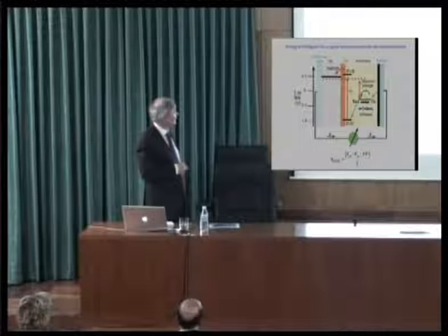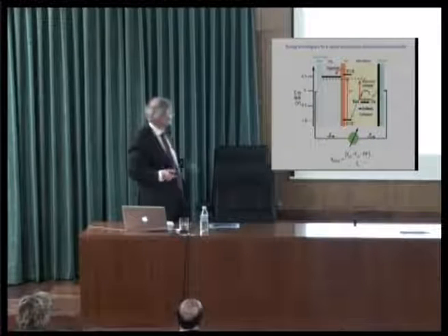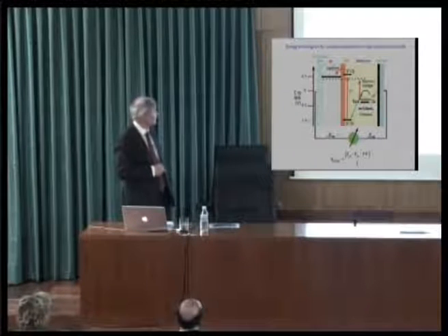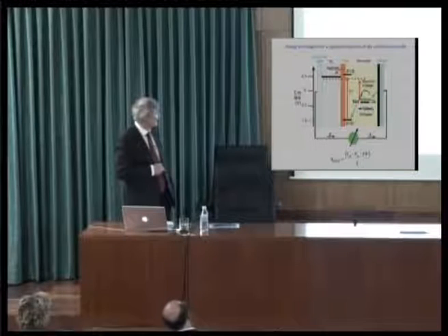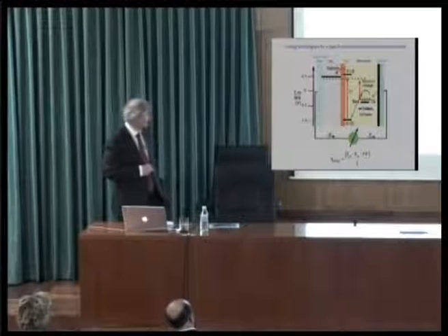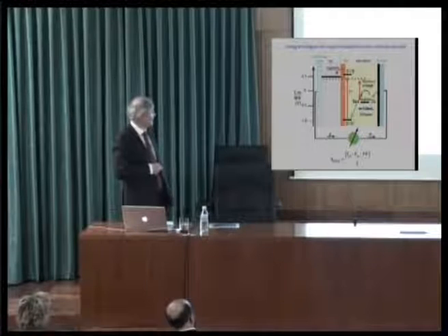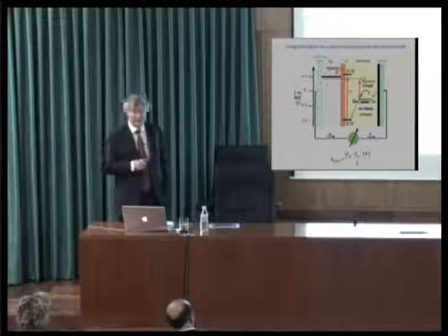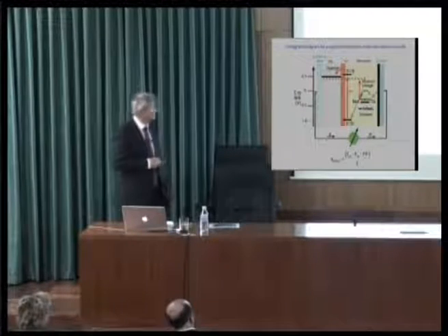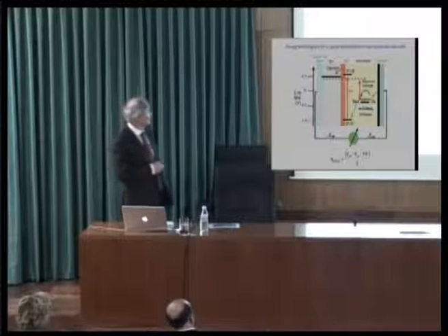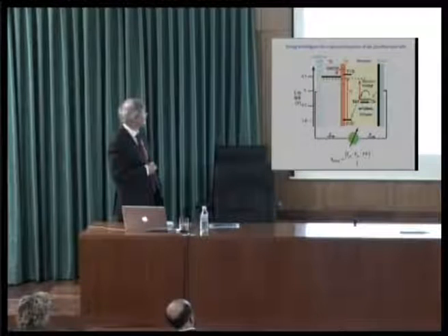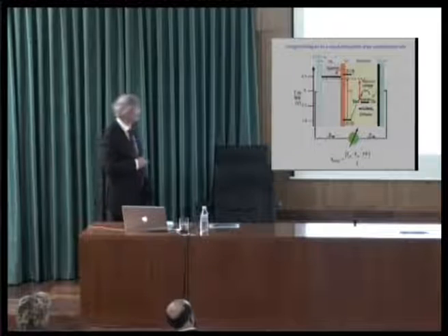Now, the hole is on the dye, the electron is in the oxide. Charges are separated. Now we need to regenerate the dye, using that redox system or hole conductor, but we haven't really matched those levels. So the Fermi level of the solution, or the Nernst potential, is 600 millivolts away from the potential of this dye. This is drawn to scale for the current cells. Very often we have this picture here. Here's my scale. It's on the hydrogen scale, but you can plot it against vacuum. 0 against hydrogen is minus 4.5 against vacuum.